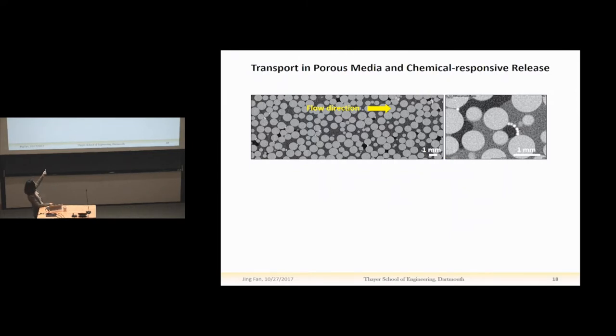And we did observe that these capsules will go to the surface of the oil blobs. And here we control the concentration of the aromatics in the model oil to make sure that these capsules will not be damaged within a few hours, so that we can still see them from the micro-CT, because micro-CT scan takes a few hours. But they do stay at the interface.